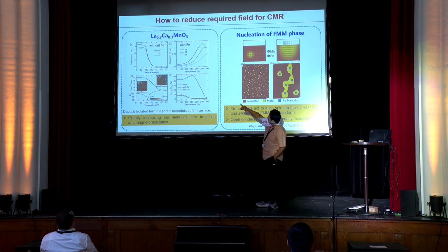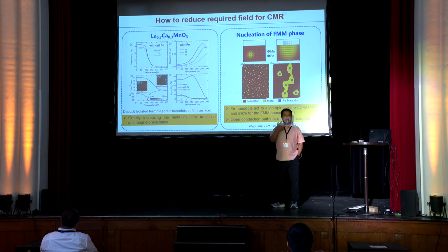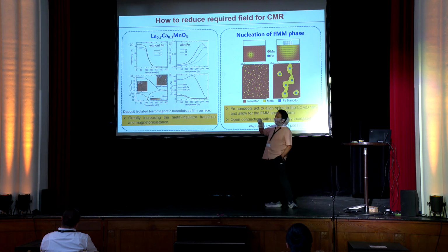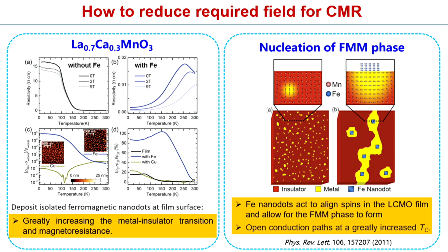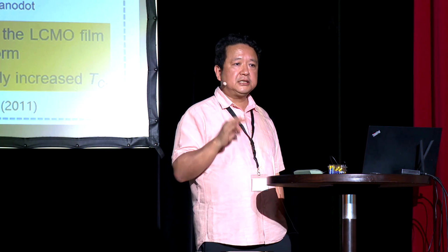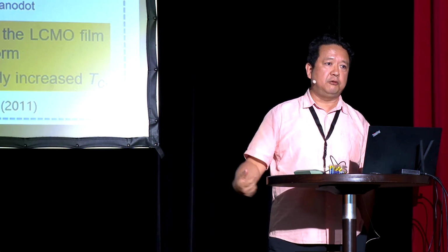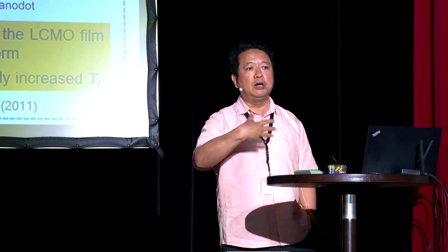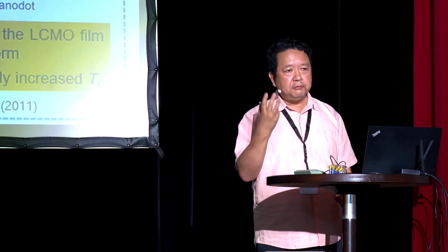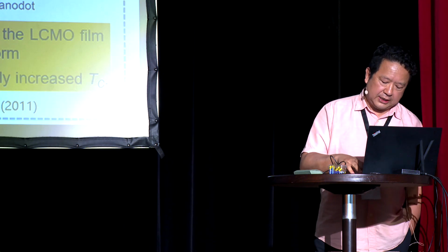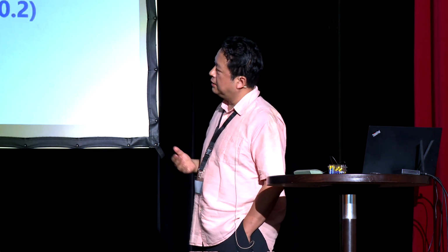On the very top left, you can see this is the LCMO film, which is in the antiferromagnetic insulating state. You put the magnetic nanodots, they are separated, so they are not conducting, but they are enough actually to create enough of this ferromagnetic metallic nucleations. And this makes this whole film become ferromagnetic metallic with a very high transition temperature, right? So the effect is enormous. So this is the idea that you can use the magnetic nanodots through this exchange field to drive this nucleation formation. And then you can use the external field to boost this growth of these nucleations. And then you can really have, hopefully, the small field driven CMR effect. So this is a way to drive this CMR effect with low field.